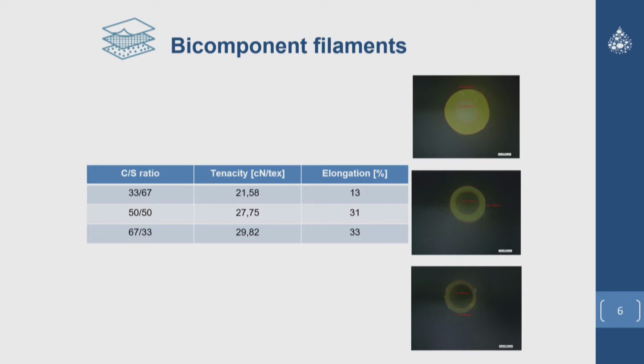There you can also choose to have different core sheath ratios. If you have a core sheath ratio from 33/67 up to the other way around, 67/33, you see that with a higher core ratio, so more reinforcement present in your filament, you have a better tenacity. You can go as high as 90/10, let's say, but then for the next step, which Chong-hei is going to explain, during compression molding, the sheath needs to form the matrix. So if you only have 10%, it's not enough to form a nice continuous matrix. So you need to find an optimum between the tenacity, the strength you need, but also still be able to process it further on. So all the other results I'm going to show you will be of a 50-50 core sheath ratio, just to start with.